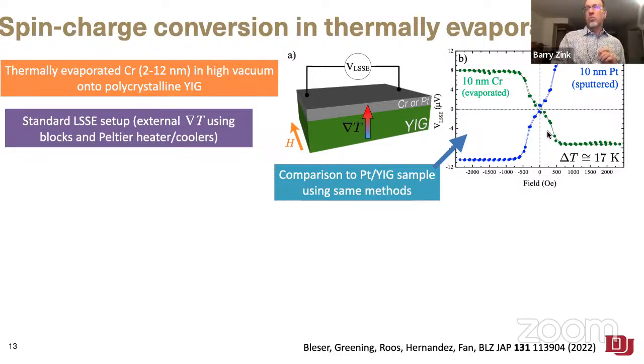So here's the first signals that we get. We can just compare the raw voltage signal for a 10 nanometer thick chromium film and a 10 nanometer thick platinum film. In this case, it's an evaporated chromium film and then a sputtered platinum film. And you see quite robust signals coming out of the chromium, which is great. But we've got to dig into this a little bit more to understand what's happening.